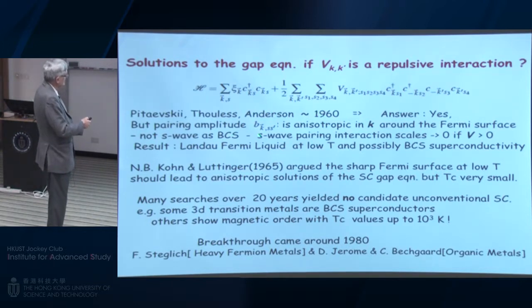But in this case, the pairing amplitude, which in BCS is essentially S-wave, essentially constant in angle around the Fermi surface, must be anisotropic. It could not be S-wave pairing as in BCS. If we have a repulsive interaction, the S-wave pairing essentially scales to 0. And in low order perturbation theory, we would just have a Fermi liquid.